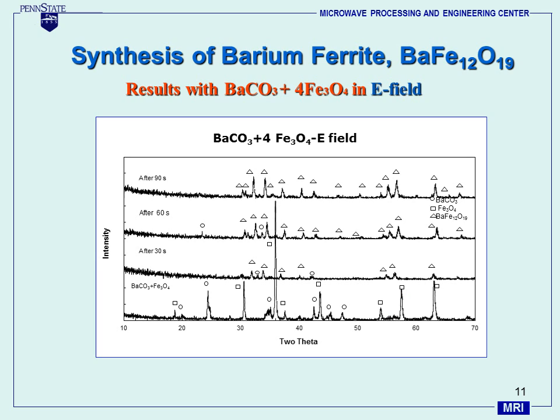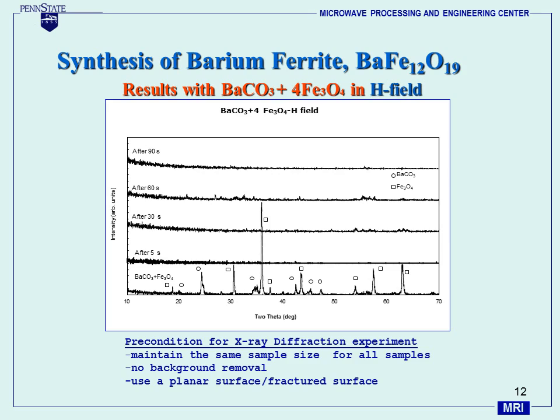So there we go. I'm going to give you just one example showing the dramatic effects. These are the X-ray diffraction patterns of the starting materials, barium carbonate and iron oxide. And you notice that after 90 seconds we've got a well crystallized barium ferrite at the top. It normally takes about 10 hours if you do it in a conventional furnace.